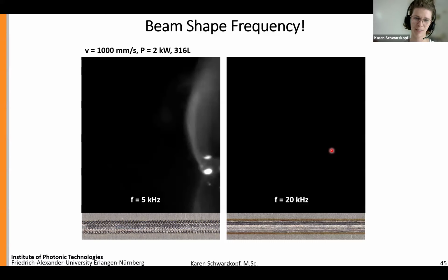But I agree that wire-based DED also has a lot of advantages. And I think one thing that needs to be considered here is that we still have the directional dependency on that. But I also know that Civan is able to really switch the beam shape depending on our direction of welding. So I see potentials here as well for the wire-based approach, especially if we're now referring back to the side lobes. I think this can be of benefit here. And again, this beam shape sequence, which allows us to switch, for instance, between the wire and laser material interaction zone itself. So these are my thoughts about that. But as I said, I've never worked with a wire-based approach.